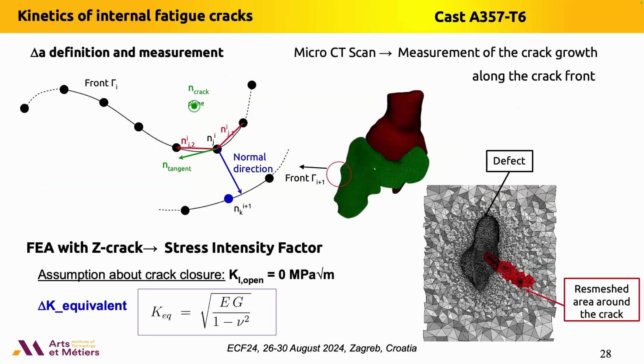So in order to reconstruct the kinetics of the cracks, we need to compute, of course, the stress intensity factor and to know the advance of the crack. The advance of the crack has been given by the 3D analysis by tomography. After meshing the defects obtained by tomography, we have decided to define the crack increment by the direction perpendicular to the crack front, so perpendicular in 3 directions because it's a 3-dimensional problem. And we have computed the stress intensity factor range by finite element analysis with the Z-cracked software. We did an elastic computation because we are in a very high cycle fatigue regime.